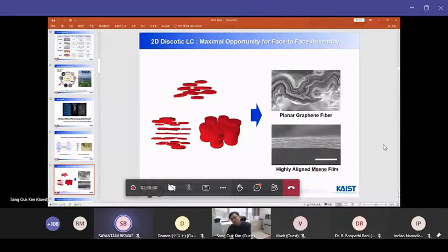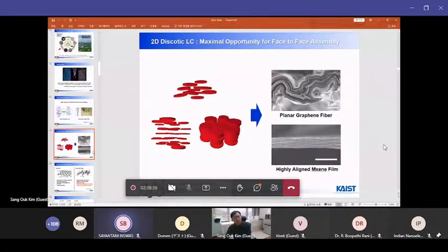The right side shows graphene fibers and a film having a highly stacked structure. Without liquid crystallinity, those 2D layers are rather randomly oriented. Even though each layer can be interesting, random stacking can yield very poor properties. But by using this liquid crystalline processing, you can get this kind of highly stacked state for optimal macroscopic properties based on the 2D structure. That's why we are interested in the liquid crystalline state of 2D materials.